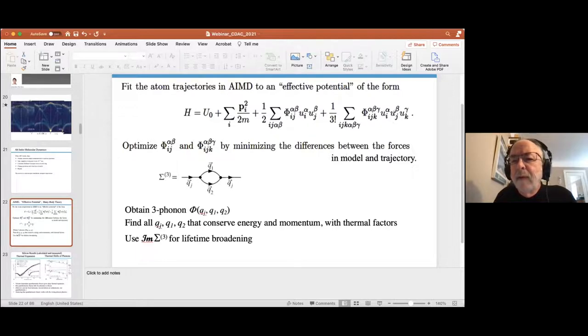When we substitute in phonon solutions here, we can get three phonon process self-energy, where we have a vertex correction here, which we get out of these fits to the effective potential to the AIMD. And we can get the imaginary and real parts of this term from a result from many body theory that I'm not showing. And the imaginary part gives us the lifetime broadening, and the real part gives us an additional energy shift, for example. So this is how we do some of these interpretations. This is an anharmonic theory. It doesn't depend just on the volume of the crystal.